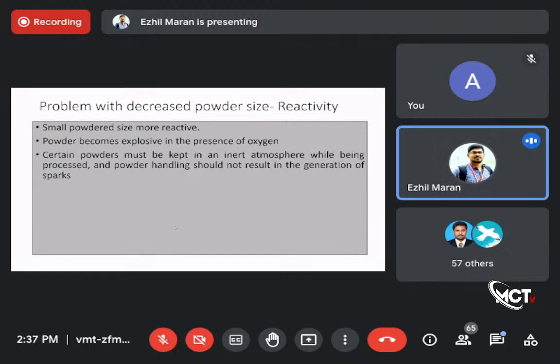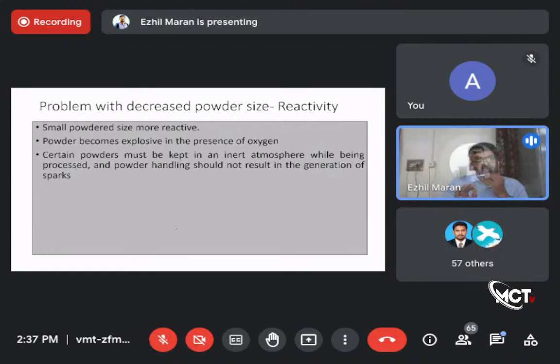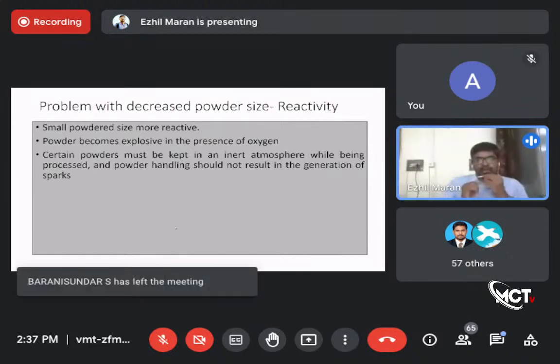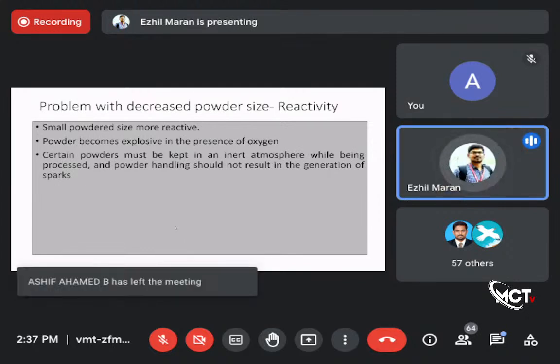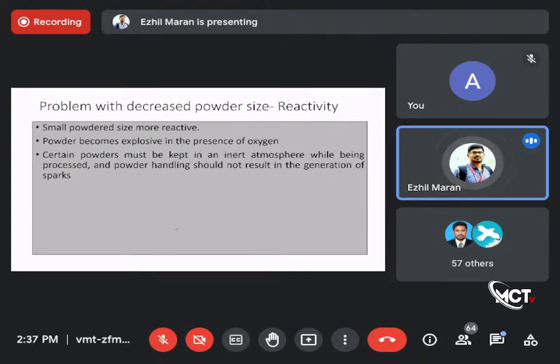And one more thing, the powder size should be very, very small. For any additive manufacturing process to be successful, the powder size should be small. That is a requirement. The lesser the powder size, the more the density. The lesser the powder size, the lesser the porosity. The powder size has a close relevance with all those quality terms. But where the issues come is reactivity. Small powder sizes are more reactive. As I said, magnesium is highly reactive. You can't go for smaller size powders.